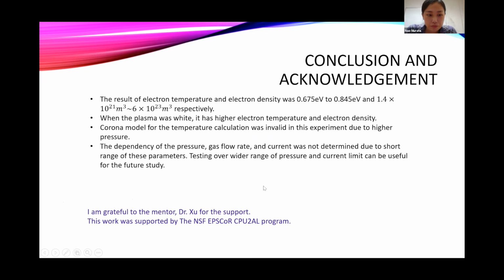So in conclusion, the result of the electron temperature is about 0.675 eV to 0.845 eV. And electron density was 1.4 times 10 to the 21 per meter cubed to 6 times 10 to the 23 per meter cubed. And when the plasma was white, it has higher electron temperature and electron density. And in this experiment, corona model was invalid because of the high pressure we used.